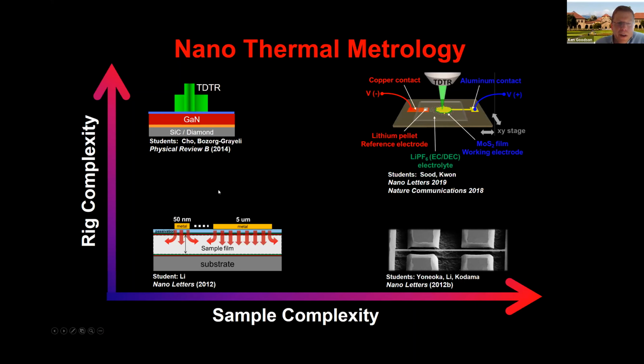But our measurements at the nanoscale involve complex rigs. So this optical setup, where you actually have pump-probe, requires a delay stage and a high-speed laser, and you use the interaction of the light with the surface to understand the heat transfer at picosecond or even below. Or you spend a lot of time fabricating nanostructures and getting current to flow down them and studying heat flow. Aditya's measurement that came out in Nature Communications in 2019,